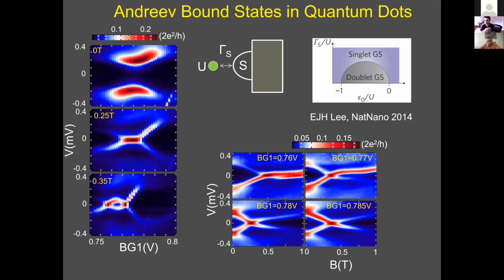Another class of explanation is just mesoscopics. As you change parameters, gates and fields, there are resonances that cross through, and they cross with some slope. For instance, it could be a slope in magnetic field. And so if there is a slope, it can create at any given cut an asymmetry, right? Because it already reached the top part, but it hasn't reached the bottom part yet. So there are a lot of different possibilities for asymmetry. Generically, similar explanations are given by STM people when they're asked about asymmetries in their tunneling spectra, right? This is also a tunneling experiment, just like what they do.